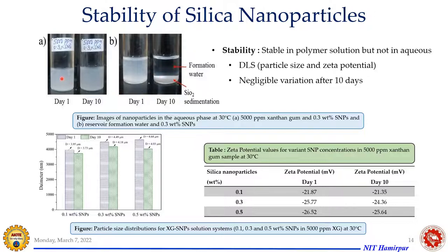Since the visual method is not a perfect way to give you an idea about the stability, apart from this visual observation, which is sedimentation behavior, we have also used different characterization techniques like DLS, that is particle size and zeta potential analysis. If you see this diagram, this gives a clear-cut idea. You can see that when you have 0.1 nanoparticle concentration, this SNPs is silica nanoparticle, which is hydrophilic in nature. On day one, the nanoparticles have more or less the same size in day one and day 10.